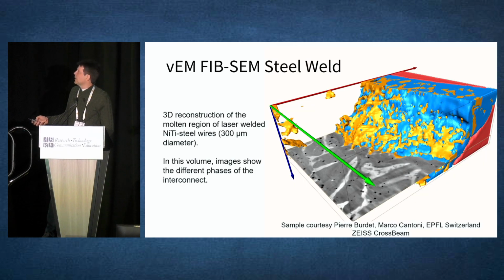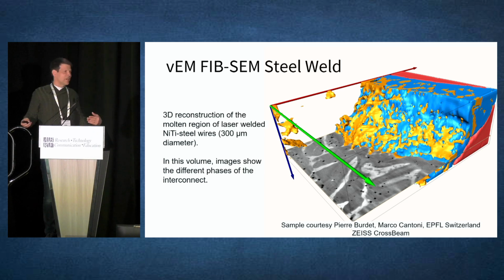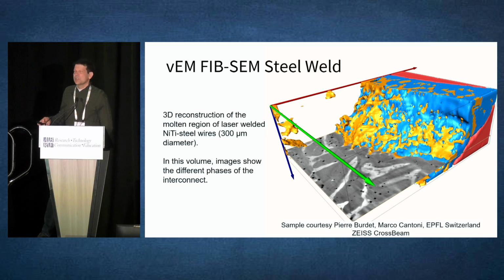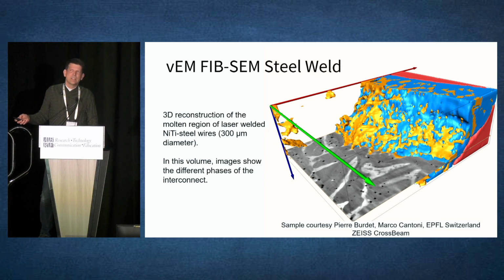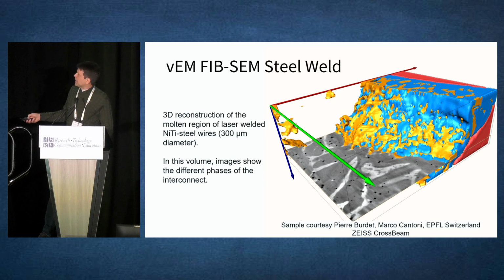And in the spirit of this cross-disciplinary idea, actually I've done some soft materials with chromatography particles. If you can contrast it in backscatter mode, you can section it, you can use a serial block face or array tomography technique. And I've done chromatography materials looking at absorption and all the pore size. But in this particular case, if you're working with hard materials, the focused ion beam is an ideal tool because it won't break your $5,000 knife or whatever knife you have. So use the ion beam here. They're using steel welds in this particular case, and they're looking for the distribution of the different elements that go into your weld when you solder these things.